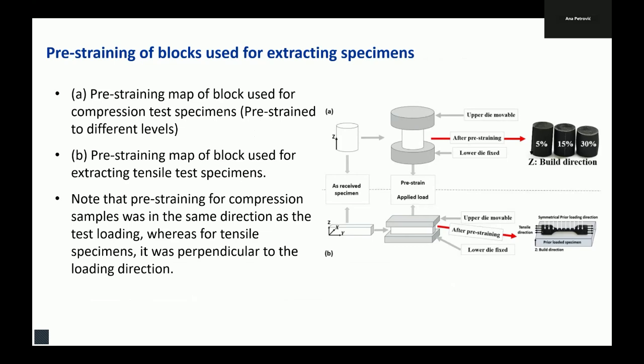So here you can see the pre-straining direction for both tension samples and the compressive samples, and different levels of pre-straining that we impose. So pre-straining for the tension is in that direction, whereas the loading will be in a transverse direction. But for the compression test, the pre-straining and the loading is in the same direction, obviously.